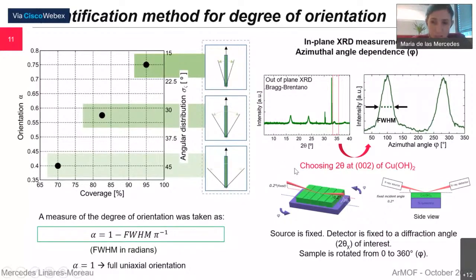What's interesting, and I'm not discussing it in detail here, but you can find more info in the paper, is that our friends Thomas and Egbert calculated that the real angular distribution of the nanobelts of the physical system is directly related to the width of our azimuthal profile measurement. So really, this value is a measure of the dispersion in the positions and the angular distribution of the nanobelts. We call this alpha the orientation, and we want to have it as high as possible.